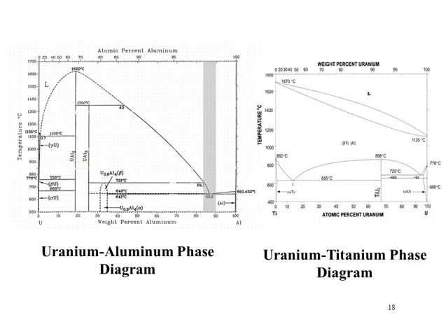If we mixed uranium with 25% aluminum by weight, it would fall right about here, and we would have a mixture of compounds based upon where it falls on this phase diagram. Over here, the 25 would be primarily the uranium aluminum 3 with a little bit of the uranium aluminum 2.